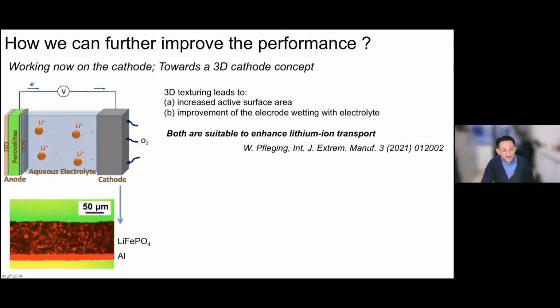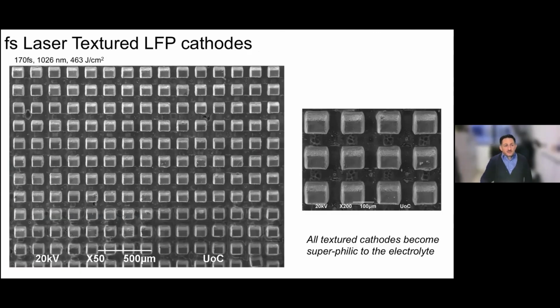So we have worked with commercially available cathodes that are used in this kind of cells. You can see here the structure of these cathodes. These are lithium iron phosphate cathodes, and this is the collecting electrode. The thickness of this cathode is about 60 or 70 micrometers. And these are the first results of texturing these LFP cathodes using a femtosecond laser. You can see that we can structure them pretty well through an ablative process, and you can reach back to the aluminum collecting electrode. And all textured cathodes showed a superphilic behavior with the electrolyte that is used in this kind of batteries.